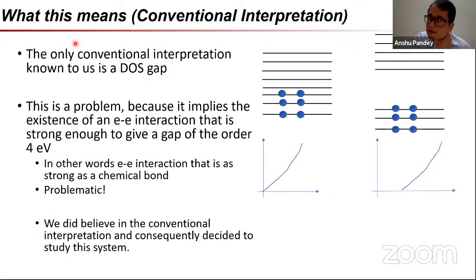So at least in the conventional interpretation that I understand for these materials, the right way to think about this would be that there is a gap in the density of states. For a normal metal, or a semiconductor, I would probably have a vanishing gap, and I can have electron excitations at all energies, and this means the material can be lossy. Electrons can scatter rather freely, and the material gets lossy. For us, because we are virtually lossless all the way up to 4 eV, my losses only build up, I don't know whether they build up after, but at least they are not there till 4 eV.